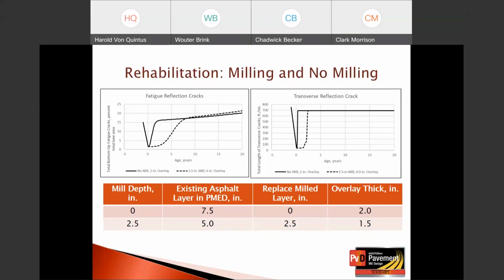The second example, we're going to mill 2.5 inches. So our existing asphalt pavement is 7.5 minus 2.5. That's 5. Our replaced milled layer is 2.5 inches. And then above that, we're going to put a 1.5 inch dense graded overlay. So the graphs at the surface show the predicted reflection cracks on the left for fatigue cracking and the prediction of transverse fatigue cracks on the right.